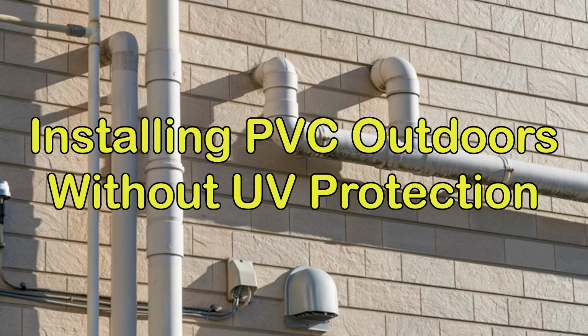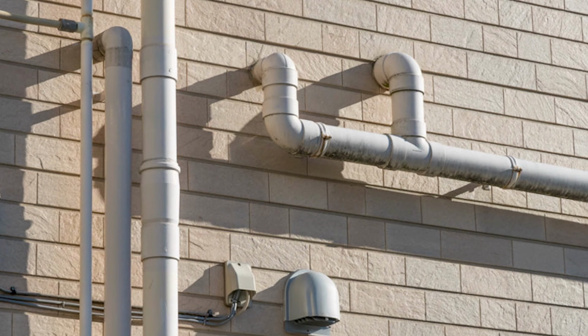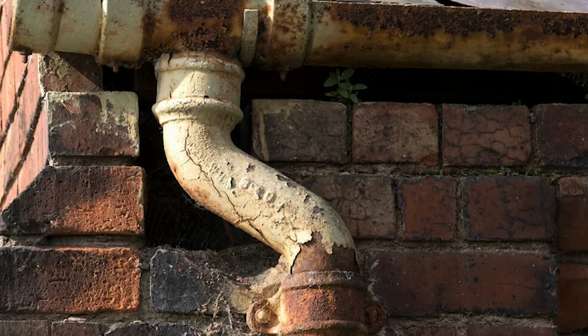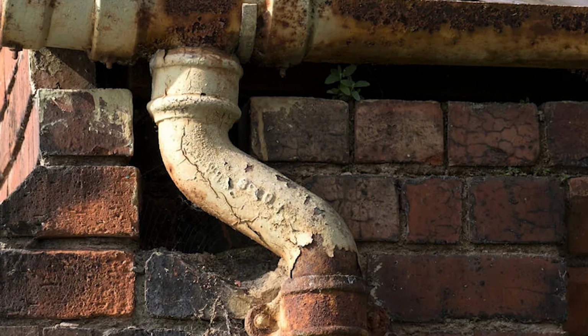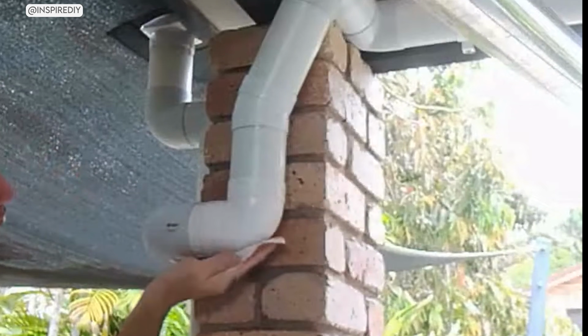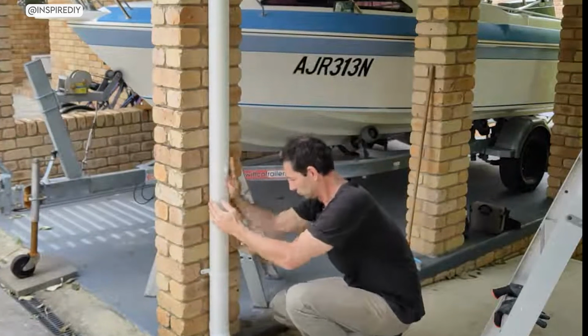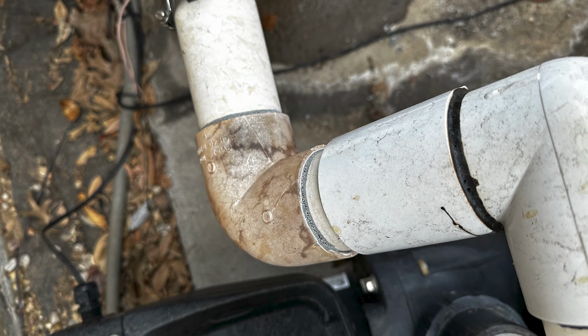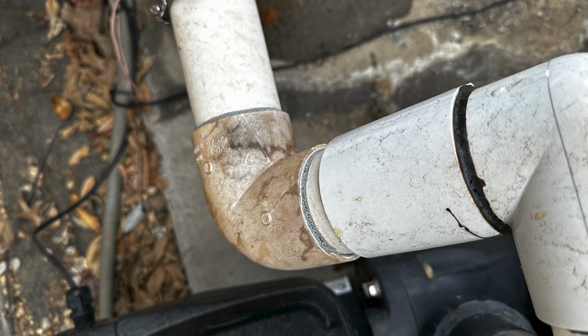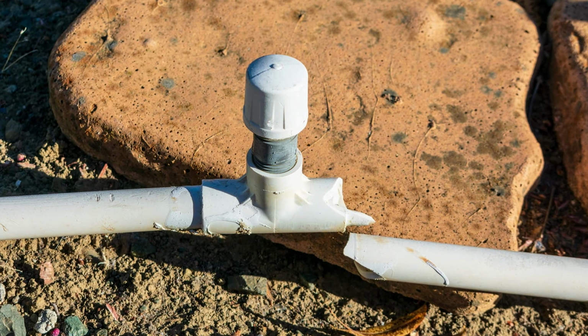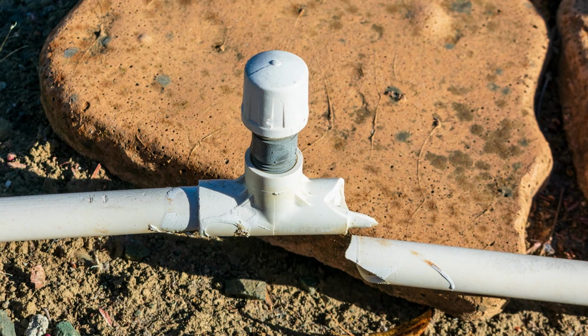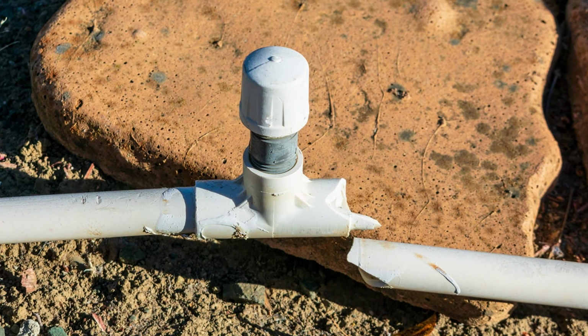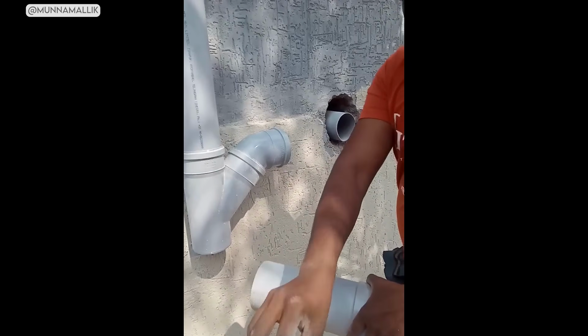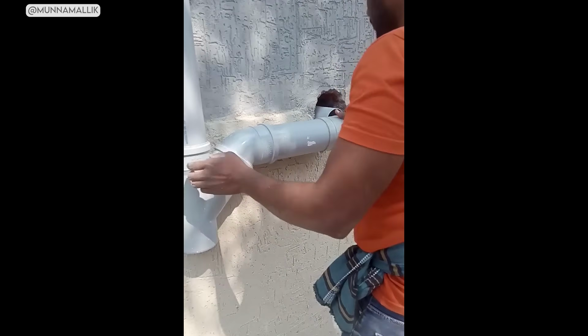The ninth item is installing PVC outdoors in direct sunlight without UV protection, and it is a mistake that ages a pipe dramatically faster than it was designed for. Ultraviolet radiation from direct sunlight degrades the polymer chains in PVC over time. The pipe becomes progressively more brittle, discolors from white to a dull yellow or chalky gray, develops surface crazing that looks like fine spiderweb cracks, and eventually fails structurally under normal water pressure or even a light physical impact. UV damage is cumulative and entirely irreversible. Once it sets into the pipe wall, there's no restoring the material to its original strength. You can only replace it.